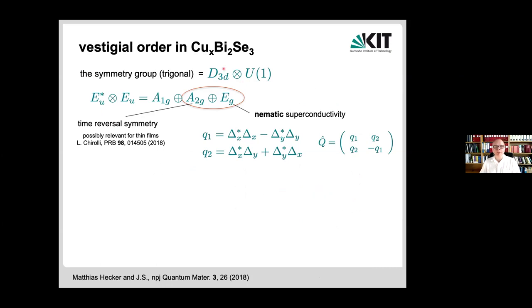We have a point group, we have an order parameter, it's EU or EG. There's some evidence that it's actually an odd parity state, but for our purposes, this is not really relevant, because both give us, as a product representation, two options for non-trivially transforming objects. One version would be that the system breaks time reversal symmetry. There's some indications this could actually be relevant in this system if you look at thin films, but all experimental indication and also theory shows that the preferred state is this nematic state.